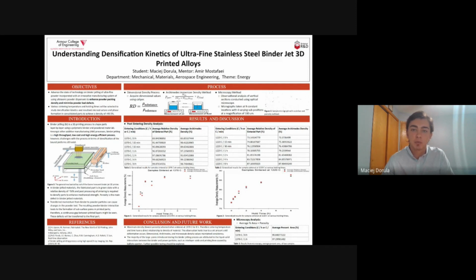After micrographs like the one shown in Figure 4 were attained, ImageJ software was then used to determine the average porosity. The dark spots suggest pores, while the lighter spots represent solid states. As displayed in Table 3, the average porosity and area decrease as sintering holding time increases. This corresponds to data determined using dimensional and Archimedes measurements.